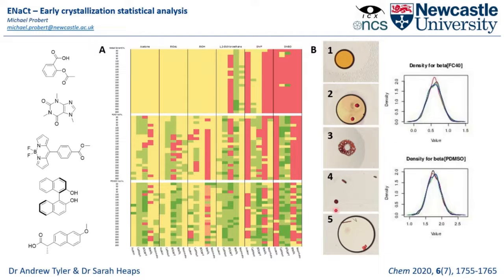We developed a categorization system for relatively rapid analysis, and then using this categorization system we could prove that the encapsulation with oil actually improved the crystallization outcome. If these peaks were centered around 0, it would have had no positive impact. If we have a value in the positive direction, this shows us we have an increased effect on success, and the counter argument would be true if it was negative.